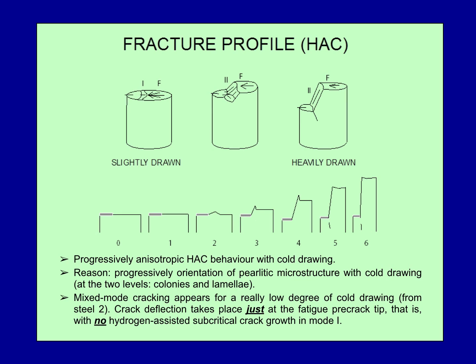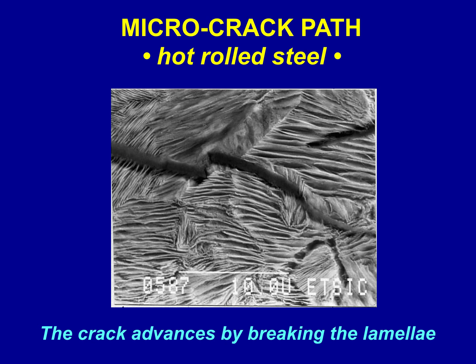Mixed mode cracking appears for a really low degree of cold drawing from steel 2, and crack deflection takes place just at the fatigue pre-crack tip, that is, with no hydrogen-assisted subcritical crack growth in mode 1. Hydrogen promotes sudden deflection, created by the microstructural anisotropy, but also enhanced by the presence of hydrogen.